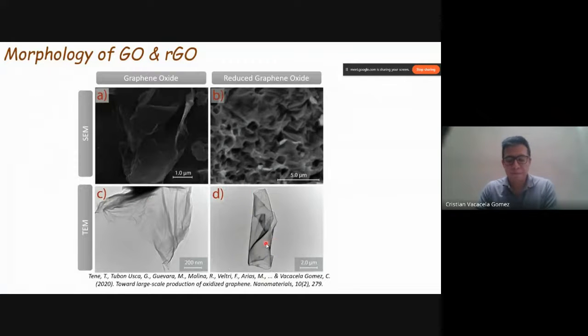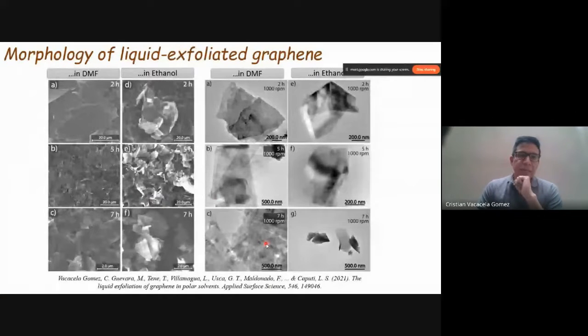Now, if we move, for example, again using the same techniques, scanning electron microscope and transmission electron microscope, and we want to analyze the exfoliation of graphene, or just the liquid exfoliated graphene in DMF or ethanol. These are very simple characteristics observed, okay? So we are observing how the surface is, how the edge is, and now here in this part we have the transmission electron microscope images.